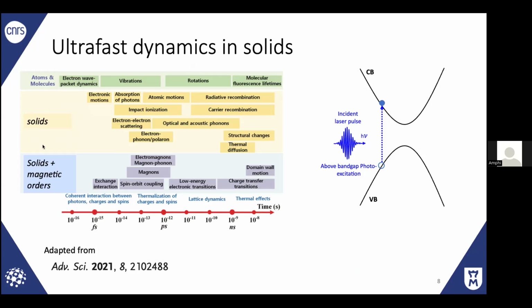So I will mainly discuss that picosecond time scale, which is really the scale where electrons and phonons interact. This is typically, as you also probably know, the lifetime of such a situation when you excite electrons with, let's say, resonant excitation, with interband excitation. Typically the lifetime of such carriers, for intraband relaxation, is around one picosecond. And during that time, when electrons are excited in such a conduction band, different processes can take place. If there is an electric field, the electron can be accelerated, but these electrons also relax and emit according to different processes. They can emit optical phonons and acoustic phonons. So this is what I would like to discuss with you today and give you a couple of examples.